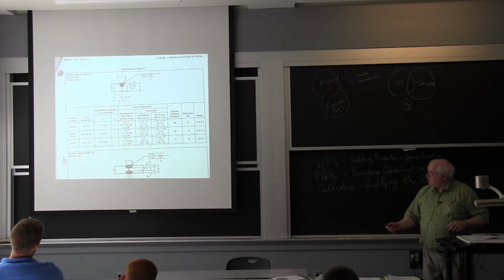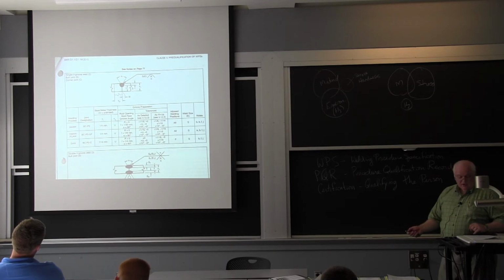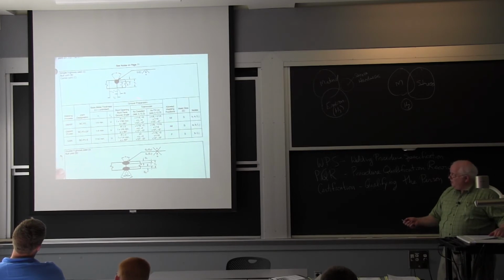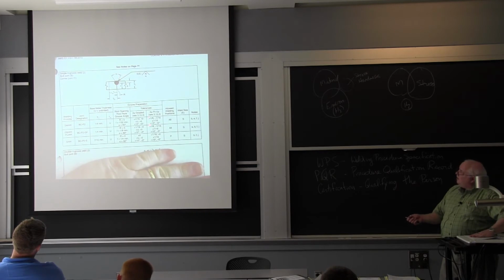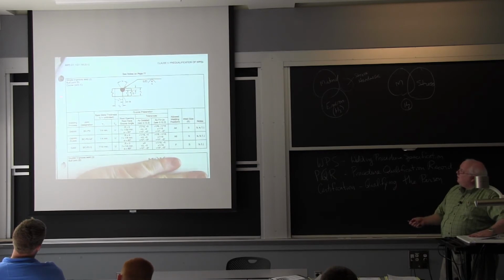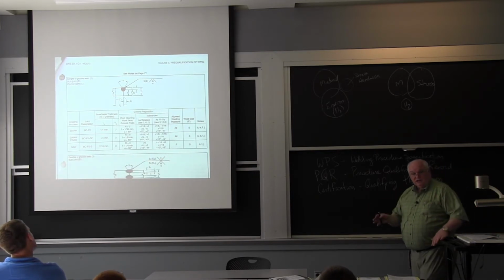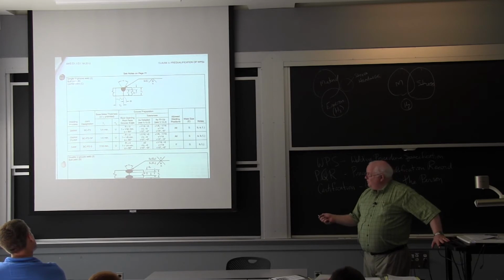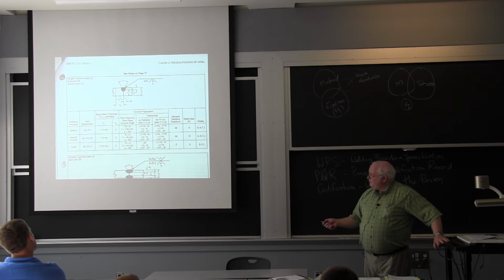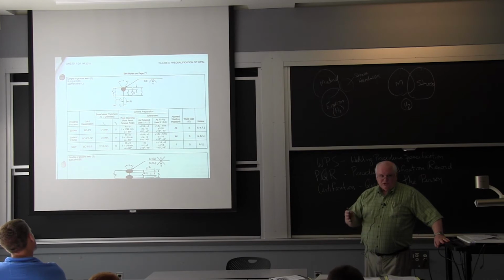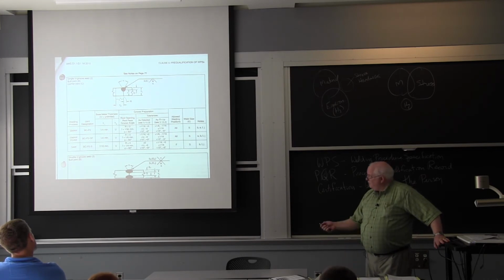And this is what the American Welding Society, when they have to write up a pre-qualified procedure, everything fits on half a page. And basically, most of the information you need for simple welds is here, rather than the page before that had a whole page of all kinds of detail, right? Because if it's simple steels, and that's what this is for, you don't have to have all that other information. It's when you get to the alloy steels and the heavy sections. But for bridges and buildings, we're not usually talking more than 1 inch thick.